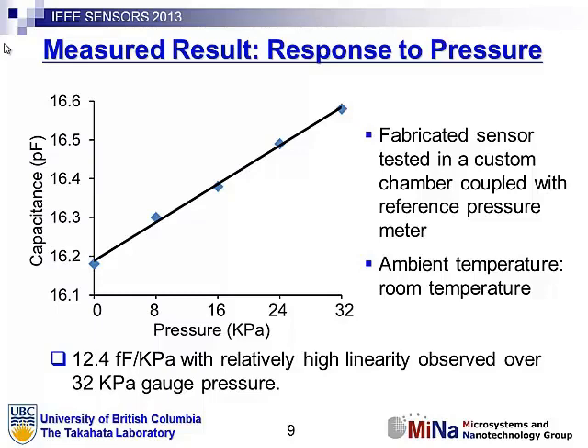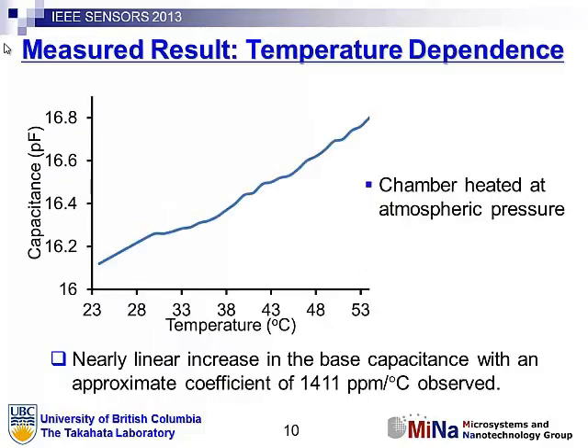And the response of, say, 0.4 picofarads with about 32 kilopascals, which is about a third of atmospheric pressure, is comparable to what you'd find in a silicon-based capacitive pressure sensor that you could buy commercially. And then the final slide